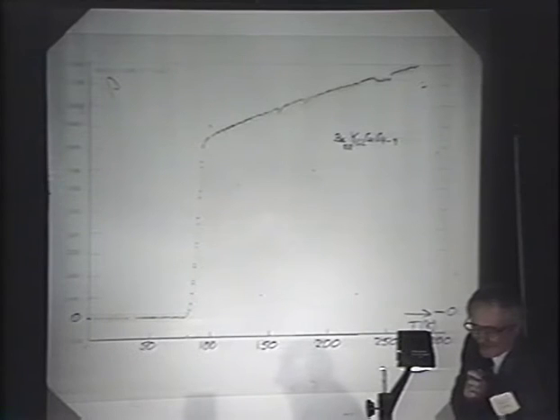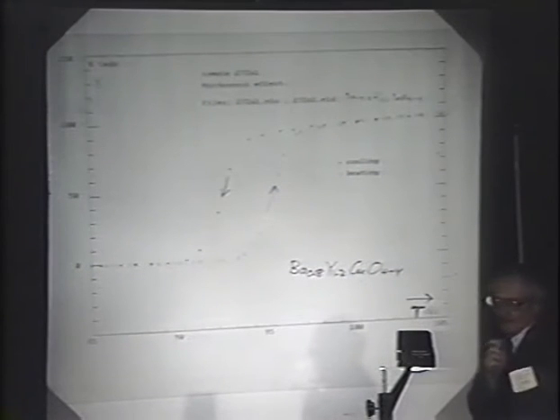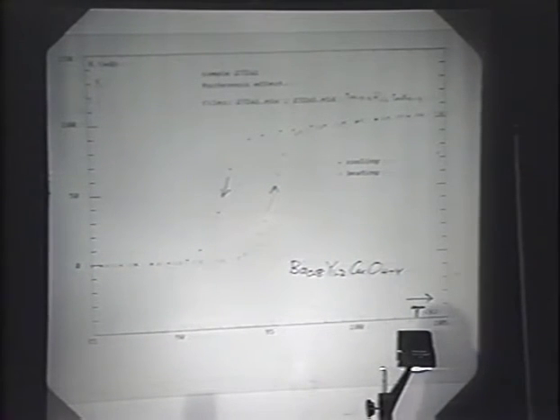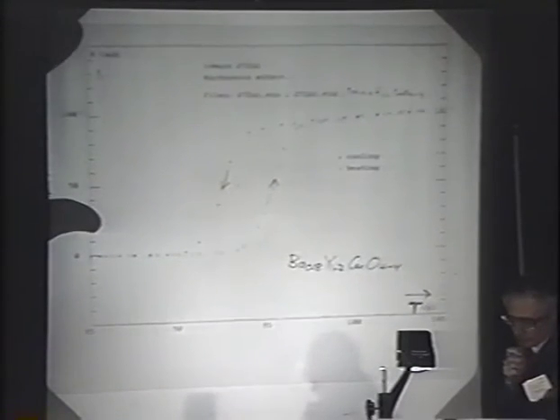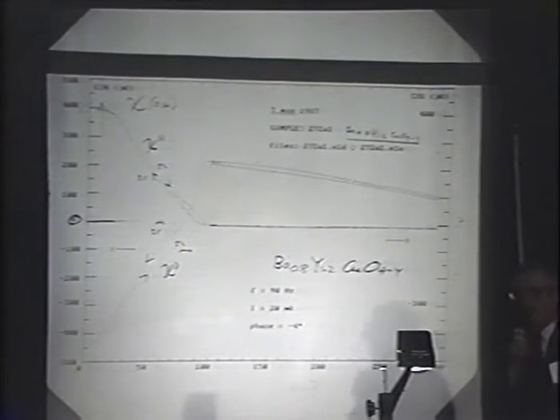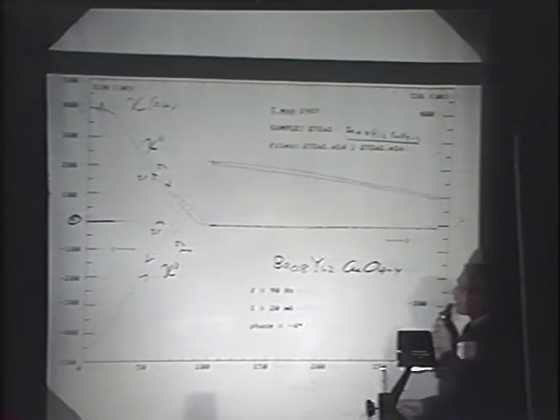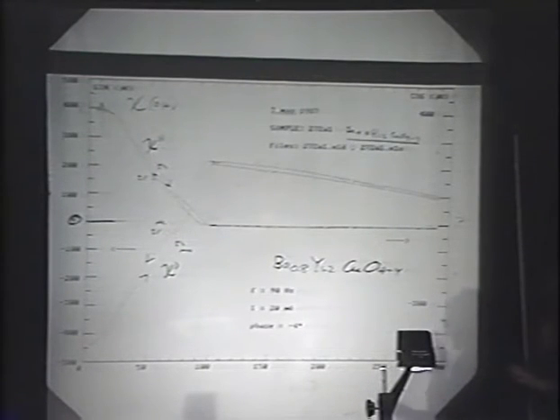We then went on a bit further for this sample to show that the resistivity blowing up became hysteretic upon cooling and heating. By cycling this, if you go through the cycle a number of times, this seems to be constant. There is a slight shift of about 3 or 4 degrees here in the resistivity, and also doing the susceptibility. Again, this is the mixed phase. The susceptibility similarly shows a hysteretic type behavior, which seems to persist all the way down to the low temperatures. In most of our studies, we have been including the imaginary part of the AC susceptibility, and that seems to be almost complementary to the real part, here in this case showing a bit of hysteresis again.